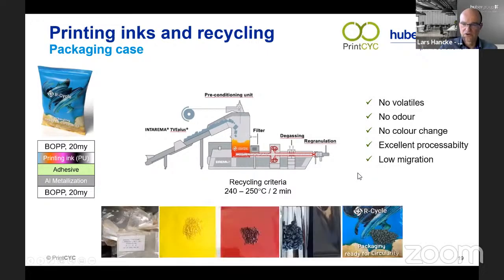To have a more visual representation of these excellent results, you find here the result of the recycling for the single material. So this is the virgin BOPP. Of course, we get, no surprise, a transparent recyclate, but also we use materials printed with yellow and with red only because these pigments are more sensitive to high temperatures than, for instance, a black, a white, or a blue. But again, the shade is almost the same as for the starting materials, so the color is stable.